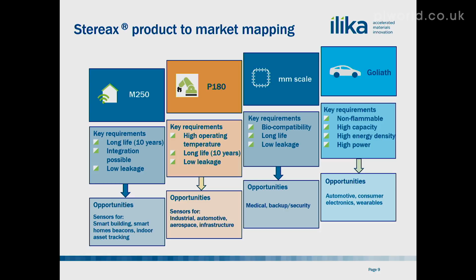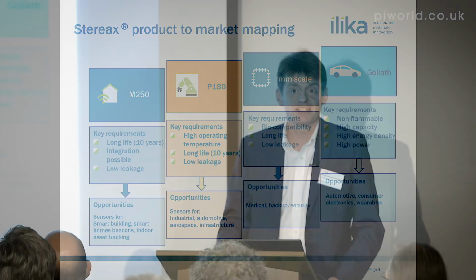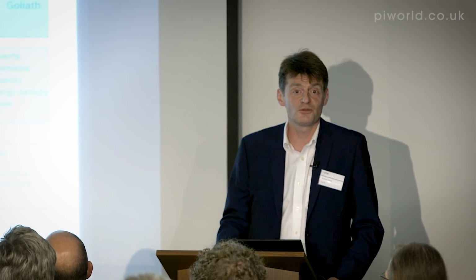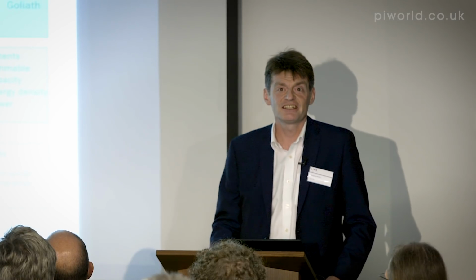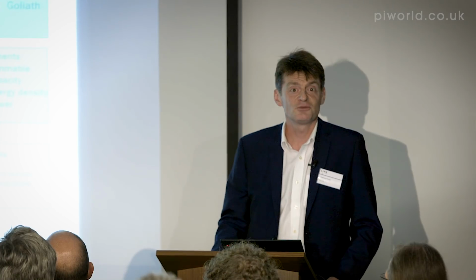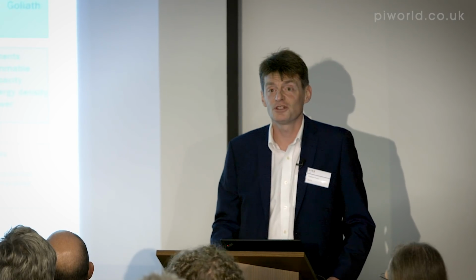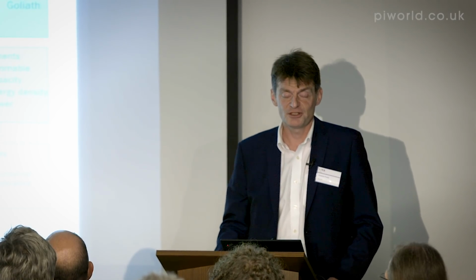The P180 is heavily differentiated from standard lithium-ion cells, which can go up to about 60 degrees C before they start to swell. If you take a lithium-ion battery to 150 degrees C, you might be lucky enough to witness a thermal runaway reaction, which can be quite impressive. The solid-state cells are very stable under those conditions and will continue to function. In fact, they even work better at elevated temperature.